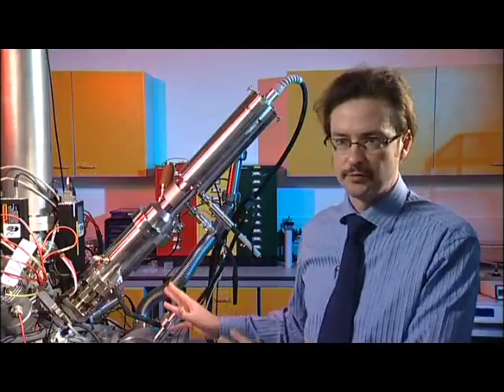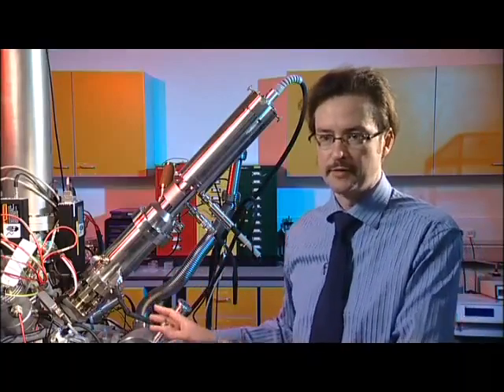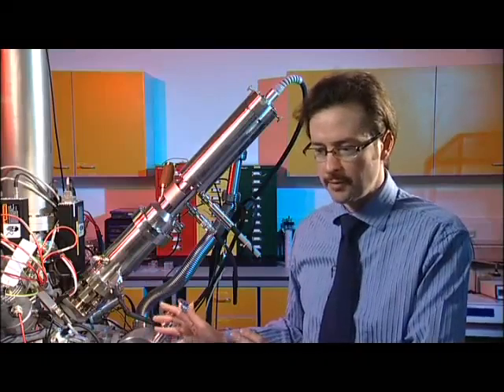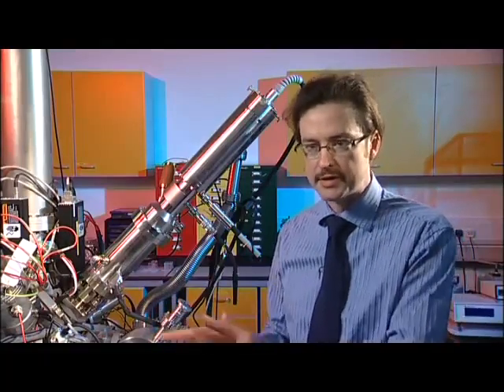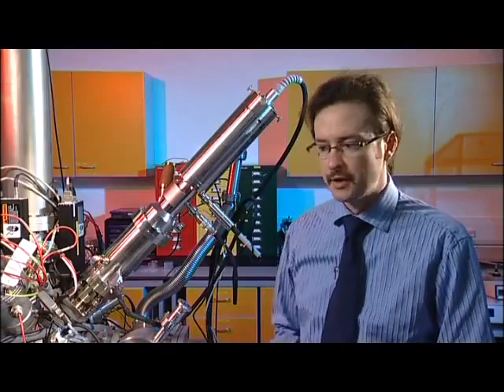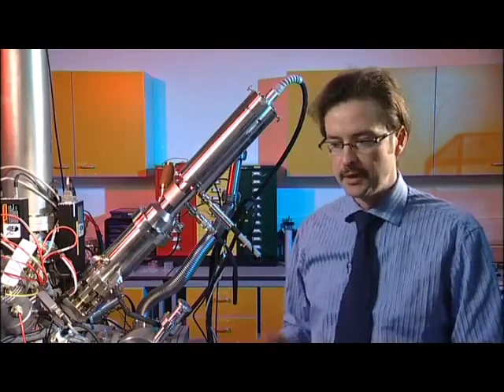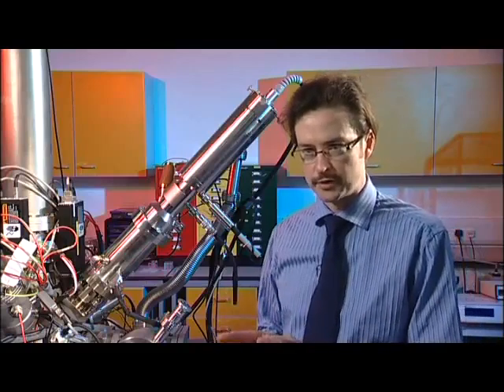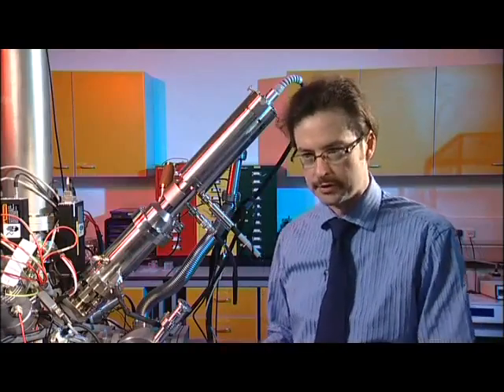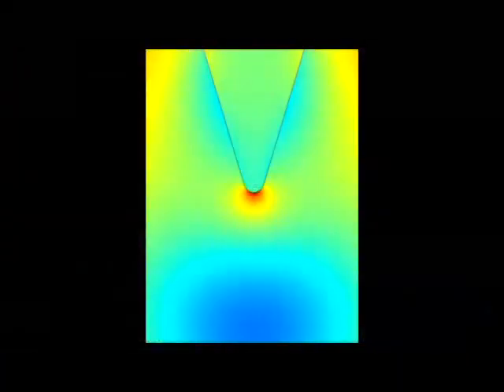For nanotechnologies, a major measurement challenge has been able to get more chemical information at the nanoscale. Most of the techniques that we have, such as techniques like this, as we drive down the spatial resolution, we get less and less molecular specific information. So we recognized some time ago at NPL that there was a major capability gap in this nanoscale domain. So we looked at the different possible techniques that could be used to address that. And the technique that we felt was most relevant was tip-enhanced Raman spectroscopy. This allows us to get Raman spectroscopy, which is normally limited to micron resolution because of the diffraction limit. By using a near-field method, we can take that resolution right down to about 25 nanometers.